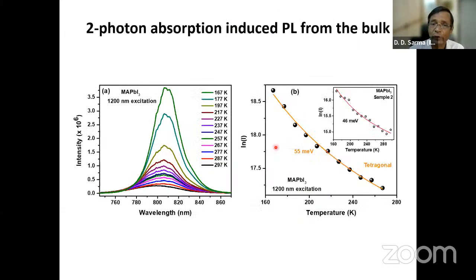The way we avoided that is by doing a 2-photon experiment, where we go deep down into the sample, which is stable, because all this effect happens near the surface. With a single photon, since it has very strong absorption, you get signal only from the surface, and the surface gets affected by evacuation. But in the 2-photon experiment, each photon has energy lower than the band gap, so they don't get easily absorbed. They get absorbed uniformly inside the bulk. And then you can look at the intensity pattern and how it changes.